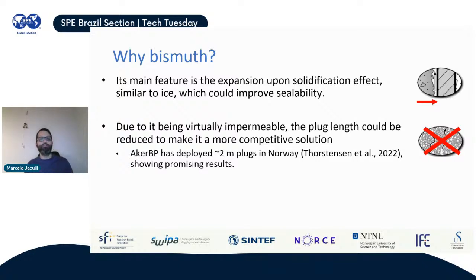So I'm saying probably because it's something that we are still studying and it's still being tested in the field. But if you manage to reduce the plug length, then that's a very good thing because you are, of course, saving material, and then it makes the solution more competitive compared to cement. So if you have a plug of cement and a plug of bismuth of the same size, the same mass of material, then of course bismuth is going to cost more than cement. But if you're able to shorten the plug and also perhaps shorten the operational time to settle this plug, then you are saving money. And then this becomes a very competitive solution.